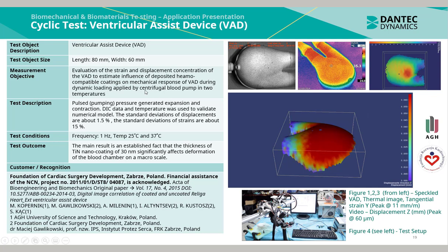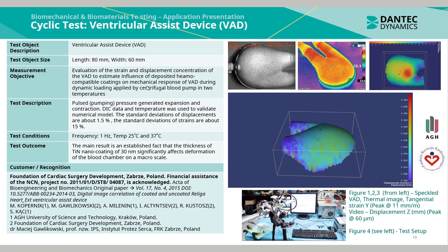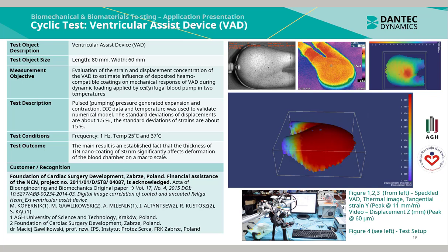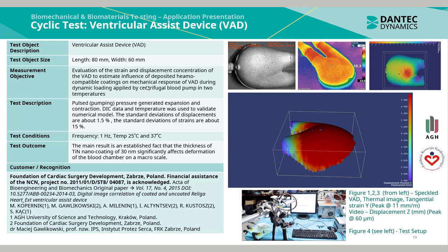The measurement objective is to evaluate the strain and displacement concentration of the VAD, to estimate the influence of the deposited hemocompatible coatings on mechanical response of the VAD during the dynamic loading, applied by using a centrifugal blood pump in two temperatures.